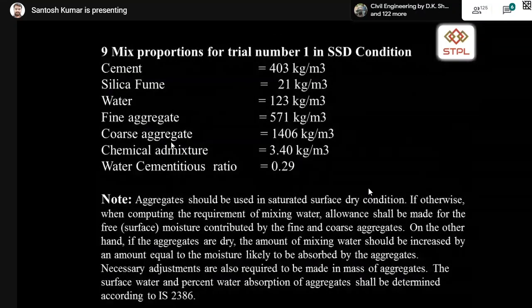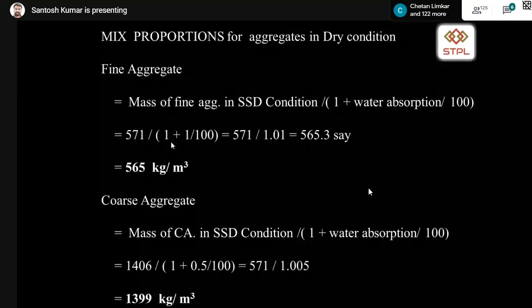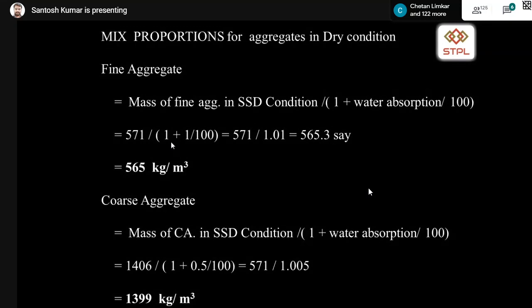When your aggregates are in dry condition, the weight of fine aggregate in SSD condition, from the previous slide, is 571 kg per cubic meter. The same 571, you have to divide by 1 plus water absorption of the aggregate divided by 100. That means you consider fine aggregate water absorption as 1. 1 plus 1 divided by 100 gives you 571 divided by 1.01. That becomes 565.3, say 565. So 6 kg per cubic meter is the water you need to add when your aggregate is in dry condition, so that it is brought into SSD condition.